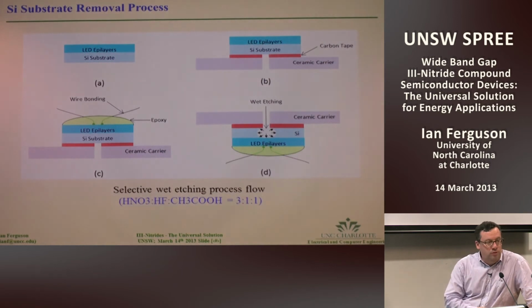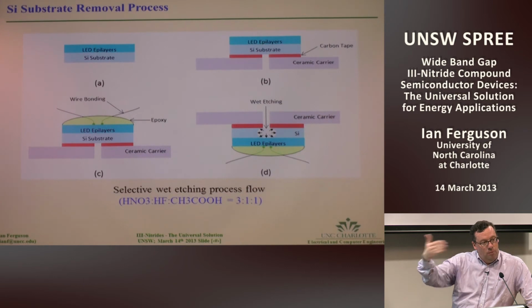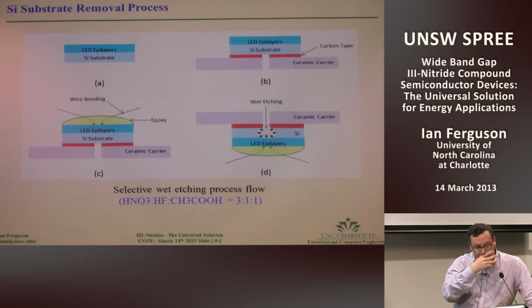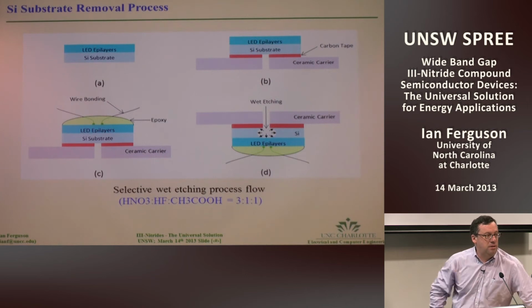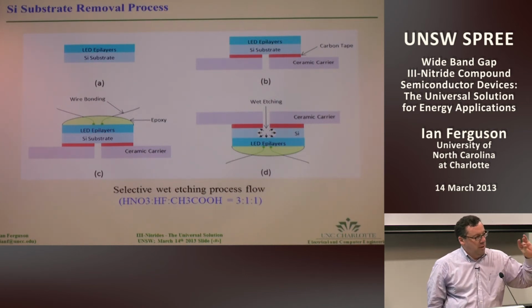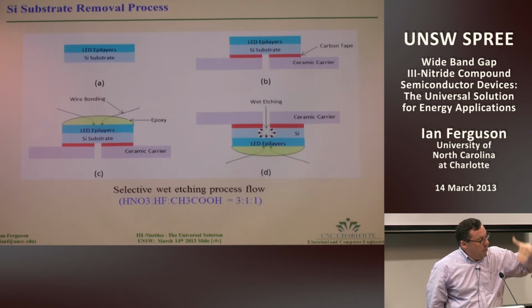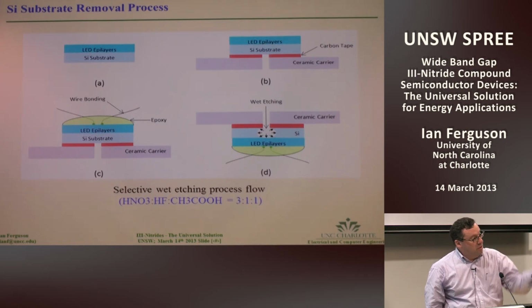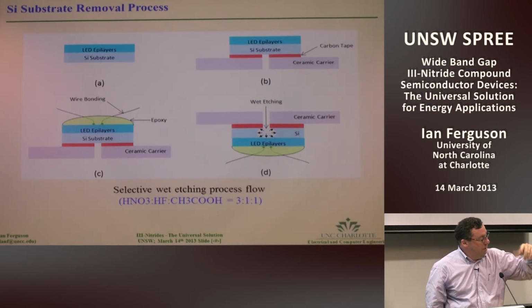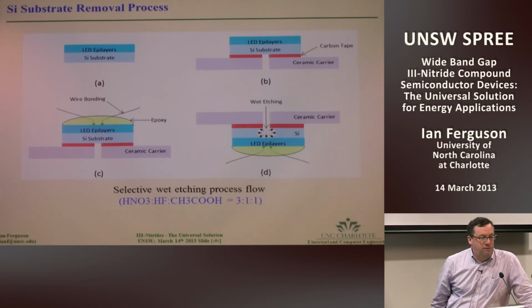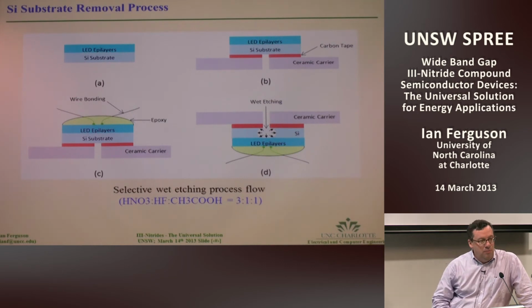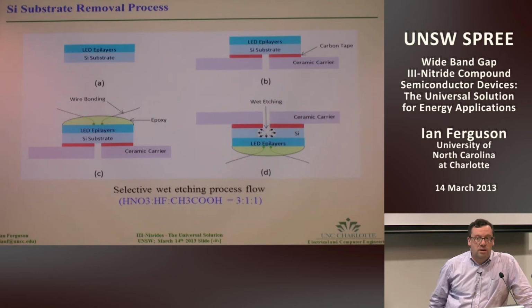The other thing we wanted to do with these devices was to actually remove the substrate. So you want to take off the silicon substrate. People were using liftoff techniques for sapphire, and this is to really improve the extraction. It's kind of a Snell's law thing. If you have a very thin layer, the light can't waveguide within the layer, so when it emits, it just comes out of the device without necessarily waveguiding. When it waveguides within the device, you tend to have losses. So the devices that have the highest EQE are typically thin GaN type devices.